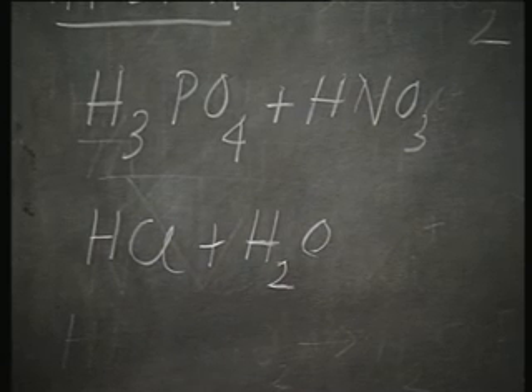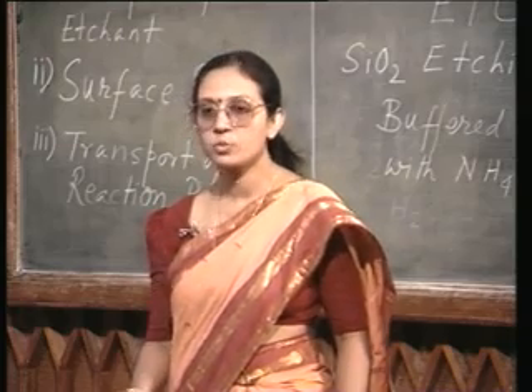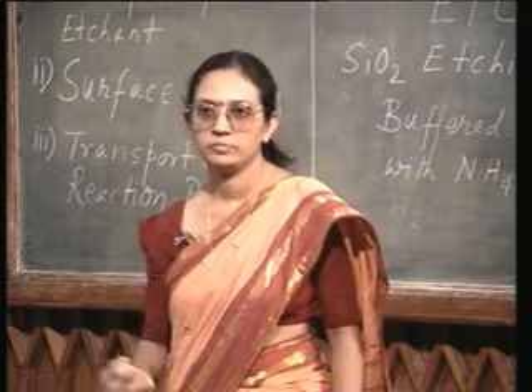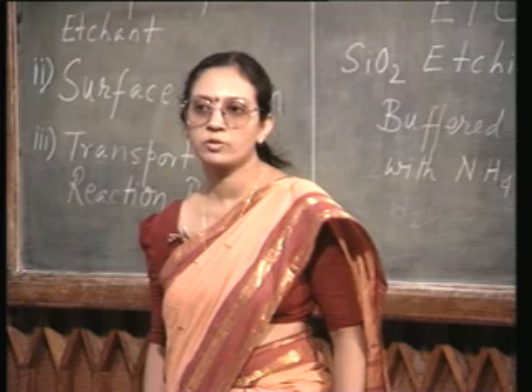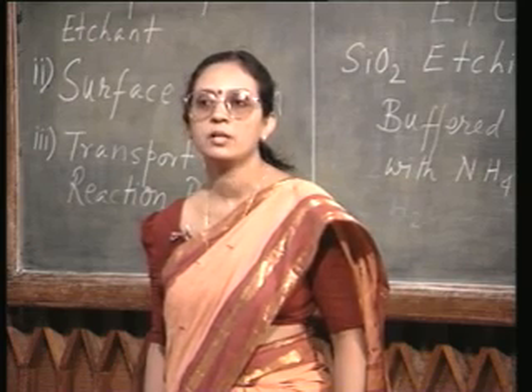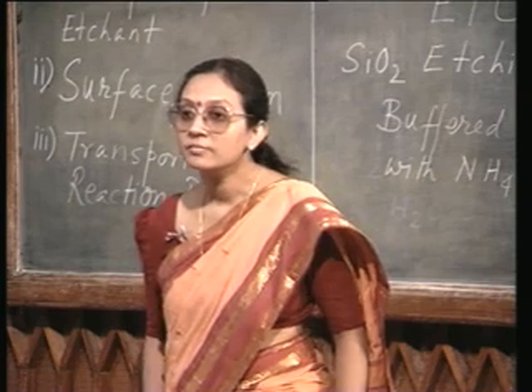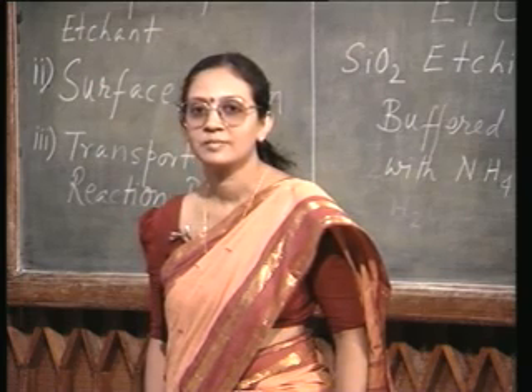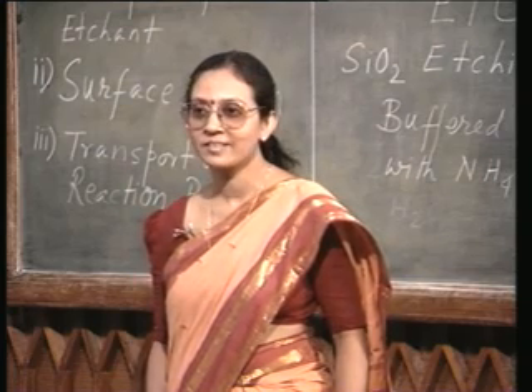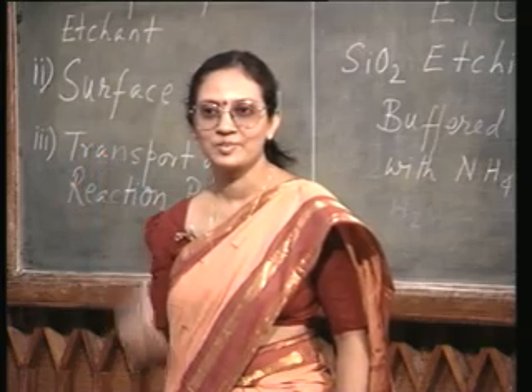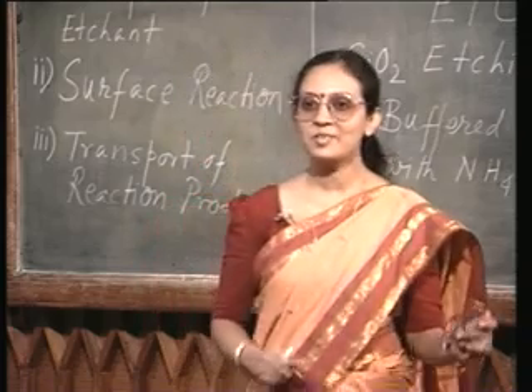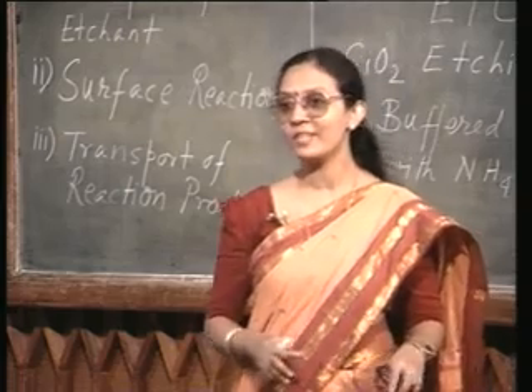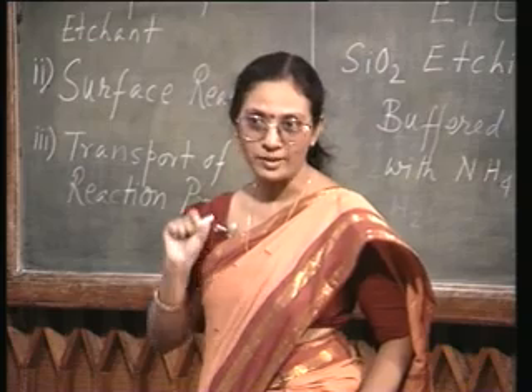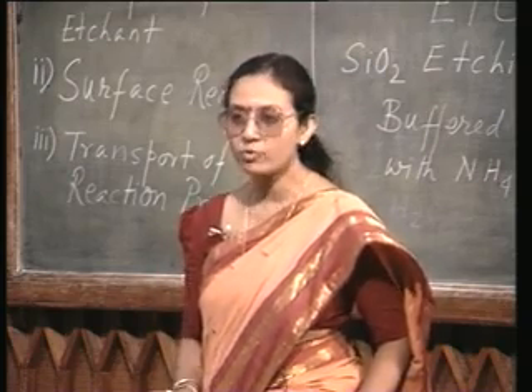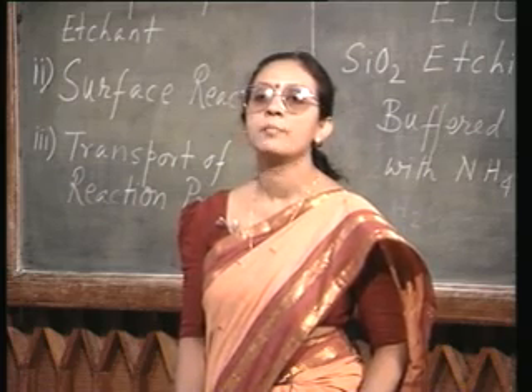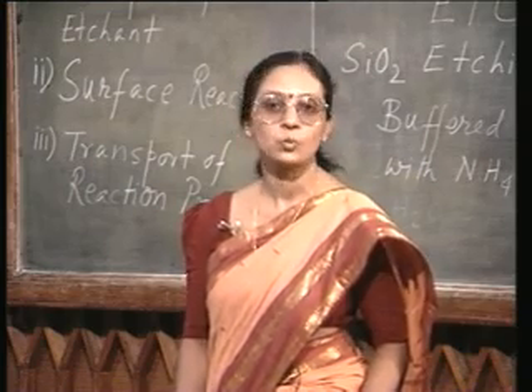Okay, let me throw a question at you. The other important material that I want to etch is gold. How does one remove gold? If you have not forgotten your high school chemistry, then you will tell me how does one remove gold. Aqua regia. Unfortunately, if I subject semiconductor material to aqua regia, that will also go. So, I cannot use aqua regia for etching gold in VLSI technology, which is a very critical point. Remember, you cannot use aqua regia to remove gold, you have to go for an alternative solution which is a mixture of potassium iodide and iodine and water.